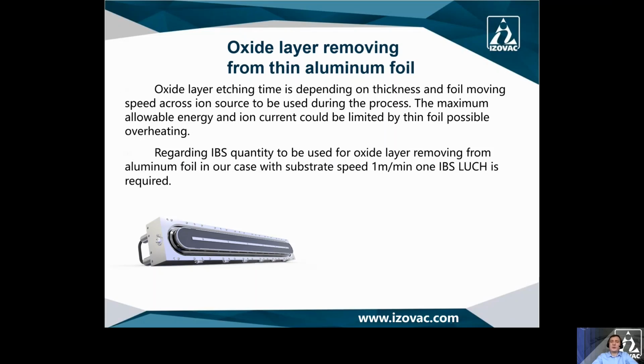Oxide layer etching time is dependent on thickness and foil moving speed across the ion source used during the process. The maximum allowable energy and ion current could be limited by possible overheating of the thin foil. Regarding IBS quantity to be used for oxide layer removing from aluminum foil, in our case with substrate speed 1 meter per minute, 1 ion source LUCH is required.